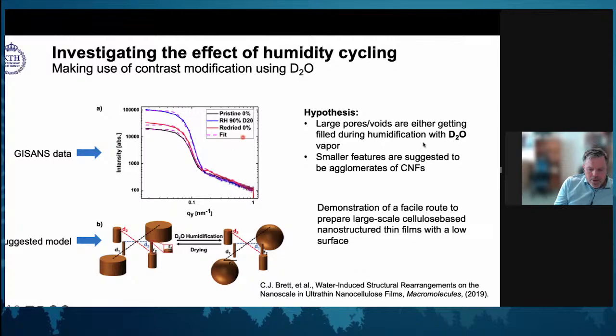The possibility we have now is by using D2O, we can use the fact that neutrons treat hydrogen and deuterium differently. It is highly absorbed by the hydrogen and not by the deuterium. So with this, we can start to look at what happens if we are adding water with deuterium. We don't see the D2O; we will see these changes in the structure, because in the cellulose, we still only have hydrogen. And by taking the grazing incidence data, with a similar type of model, we can start to explore what's happening when we're cycling humidity.